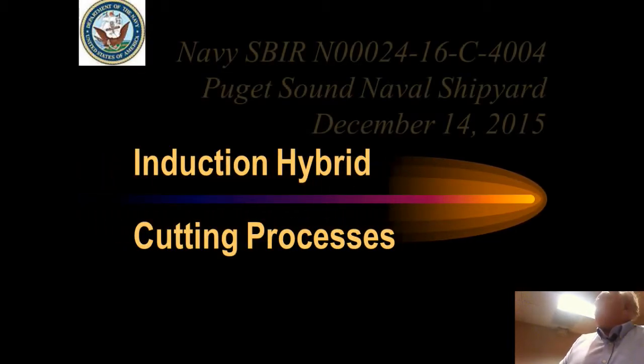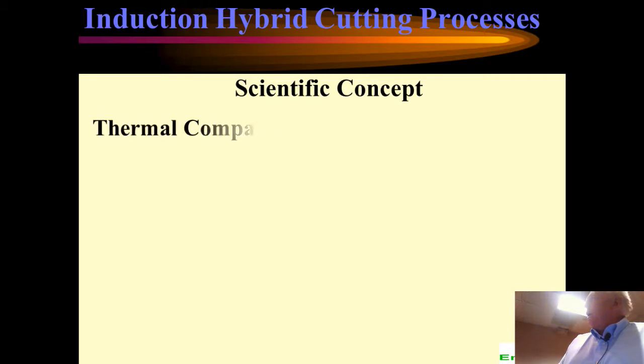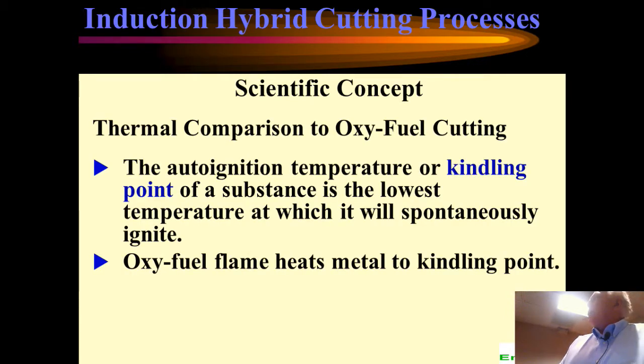All right, so we took this process and went a little further with it, and we said, okay, what if we take that induction coil and we put a cutting torch behind it instead? What might we be able to do there? The scientific concept is basically when you're using oxy-fuel cutting, the flame heats the surface of the material up to what they call the auto-ignition temperature. If you're above the auto-ignition temperature and you hit it with oxygen, it immediately turns into iron oxide, and that gives off a lot of heat as that reaction, and that's actually what's doing the cutting. So all you have to do is maintain the surface of the steel at that 1600 degree temperature and then shoot oxygen at it, and it cuts through the material.